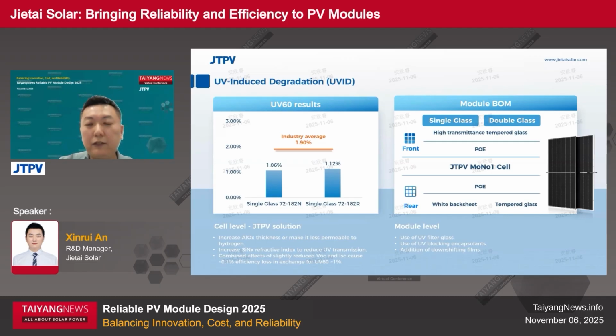And to reduce UV transmission to the cell, we tailored the silicon nitride layers at the front to a higher refractive index. And in this case, ISC is also slightly reduced. So overall, a slightly reduced VOC and ISC together may cause an efficiency loss of about 0.1%. But UV60 is greatly improved from over 2% to about 1%.